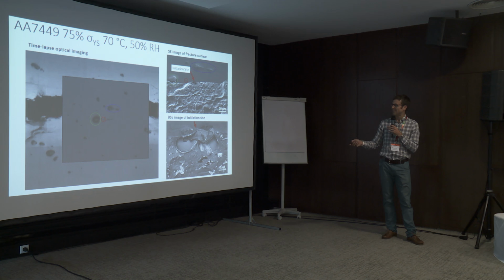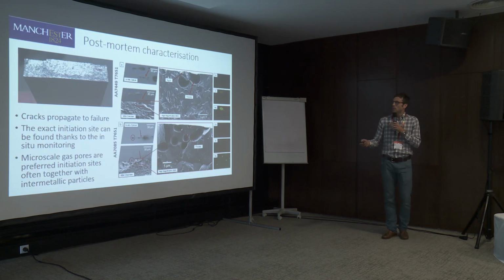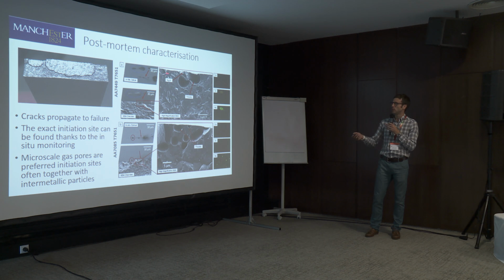But we can identify this exact initiation site, and we've now done this for numerous different sites and different materials. So here are 2 examples. We wait for the sample to crack open, so it fails naturally if we just leave the test to continue. Then with that knowledge of what's happened on the top surface, we can find these initiation sites. Here in this example of 7449 and here for 7085, we see a consistent trend, which is that these gas pores in the material seem extremely important as preferred initiation sites in this environment.